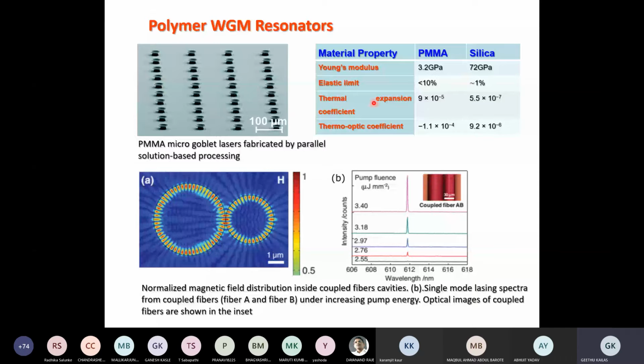You can compare the properties with silica. You have a large thermal expansion coefficient, 2 orders greater, and thermo-optic coefficient also 2 orders greater compared to silica. So it is very easy for handling polymers compared to silica. And this is an example shown. You have a circular cavity and another circular cavity, and they are joined together, and once they are coupled together, it is very easy to select the modes. So once the coupling happens, the resonance condition changes, it becomes more stringent, and you can see the resonant condition should satisfy the size of this cavity and the size of this cavity, so that it is very easy to modulate or select the frequency that is coming out.